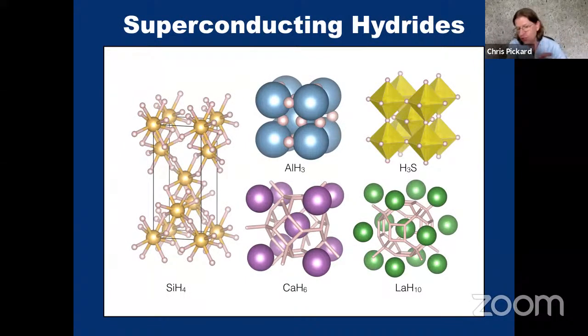So the story started with silane. It was proposed that it would be a superconductor. I found that it was semiconducting. Mikhail Eremets actually did experiments on this and did find it to be superconducting, but the interpretation of those experiments had probably swung around to thinking he'd made some platinum or some transition metal hydride rather than the silicon hydride. But what he did find experimentally was precisely the structure that I'm showing here, this silane structure that we predicted with AIRSS.